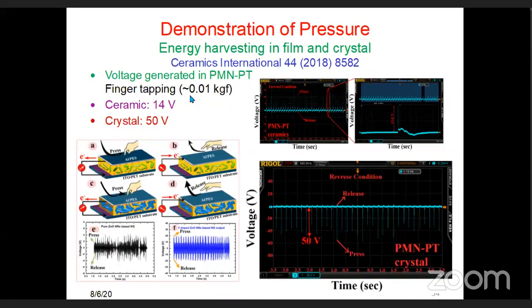If this is a device, I press it with a finger, release it, and we get voltages out of it. This is the output of a PMN-PT ceramic. You can see that in the case of ceramic, the output voltage was nearly 14 volts. But when we put the crystal as a whole without grinding it, we achieved up to 50 volts on pressing. This is the output voltage because of the pressing of your material.